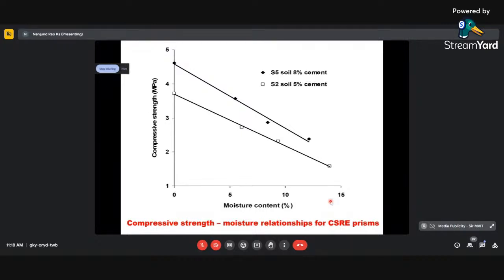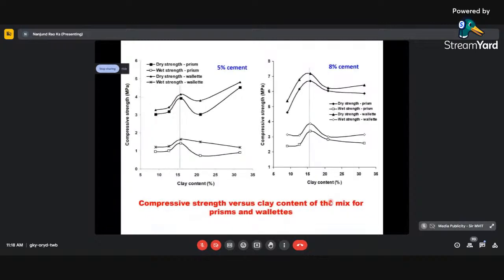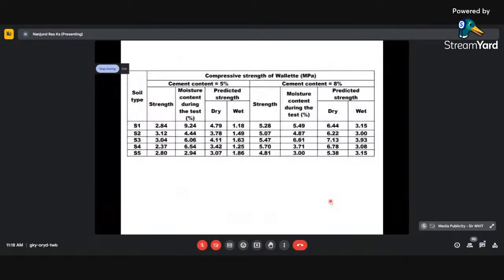That is compressive strength relationship with moisture content at time of testing. This is how the clay content in the soil impacts the compressive strength. And I mentioned to you the optimum that we have found is 15% or 16% clay, for both 5% cement and 8% cement. We found that the range is somewhere between 15 to 18, 19% clay content, which will give you the highest strength and also durability.